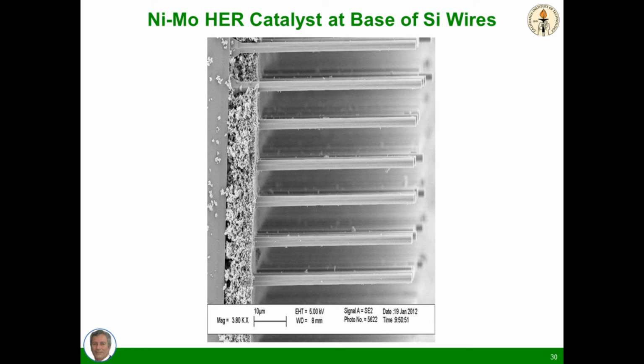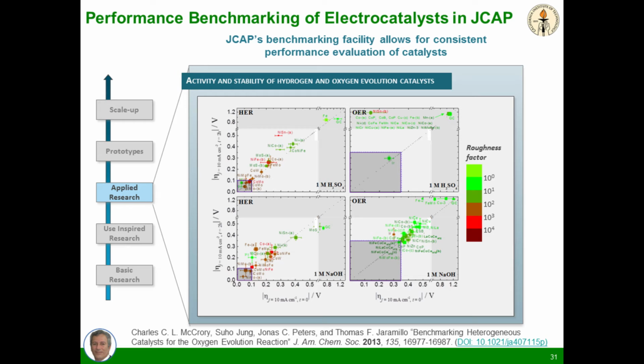The next slide shows how much there is to be gained by further changes in the electrocatalyst overpotential. It was performed by the benchmarking group in the Joint Center for Artificial Photosynthesis and shows that the hot zone, so-called, these shaded squares in the lower left corner of these plots, which each represent on the x-axis the activity, the overpotential, where lower is more active, as a function of the initial time of measurement, and then on the y-axis, the same quantity 2 hours later to give an indication of stability.